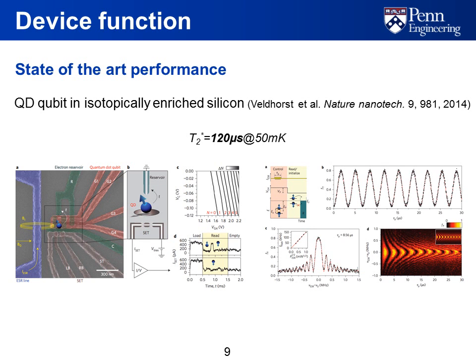Moving to the state-of-the-art performance, people developed quantum dots in isotopically enriched silicon in 2014, which gives a 120 microsecond coherence time, which is several orders of magnitude enhancement.